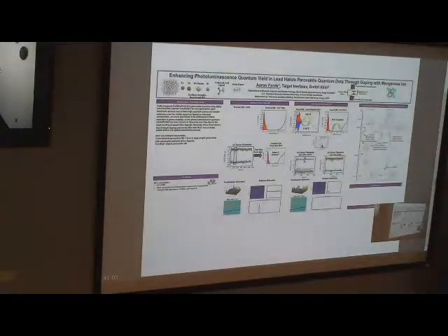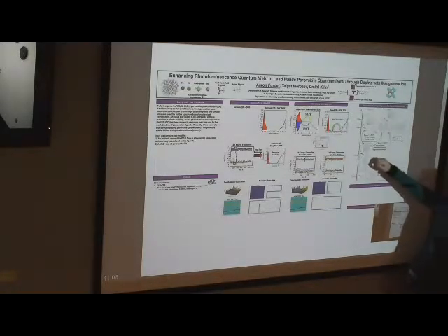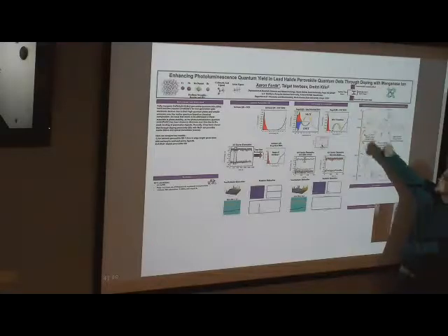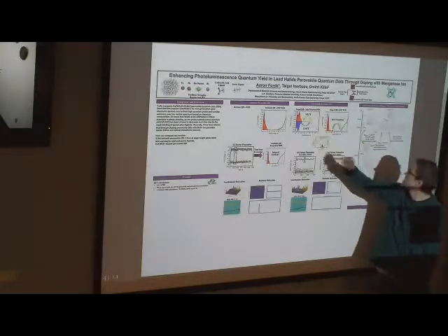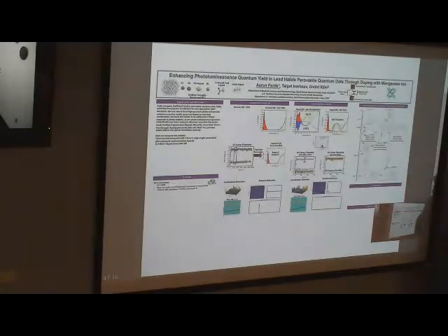For the spin up transitions, we can have a metal to ligand charge transfer, MLCT, which is shown in our density of states there. And then we can also have a ligand to metal charge transfer. Those can happen in the spin polarized cases because spin is a good quantum number and you can't have a spin flip in that basis set.